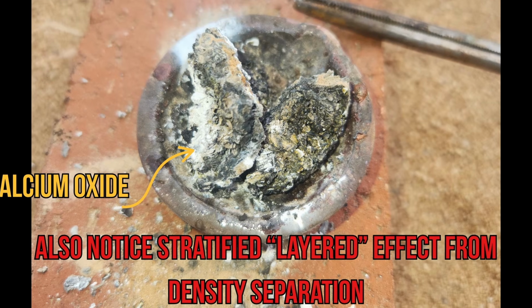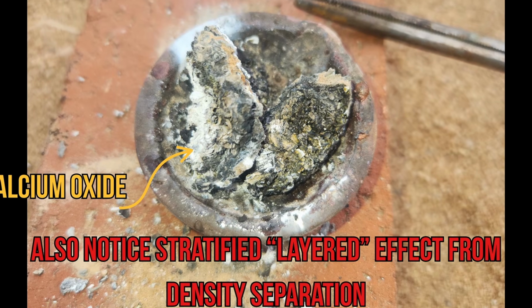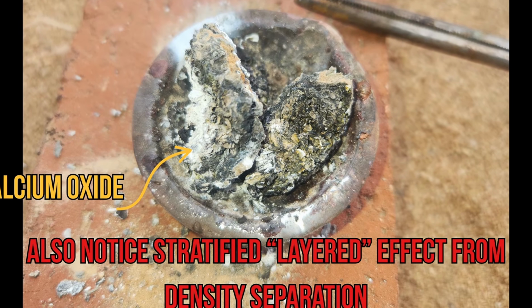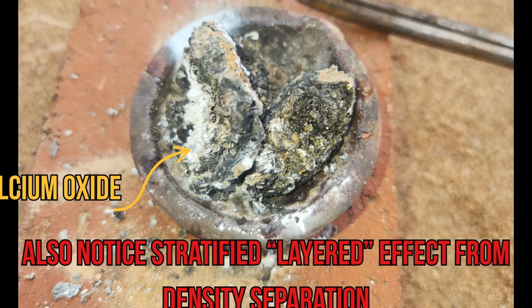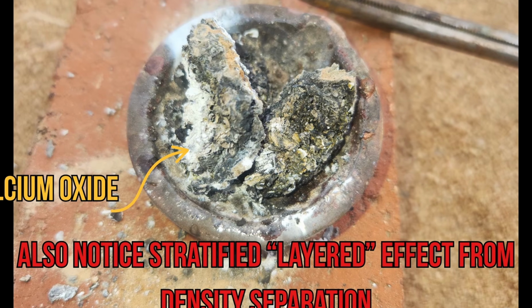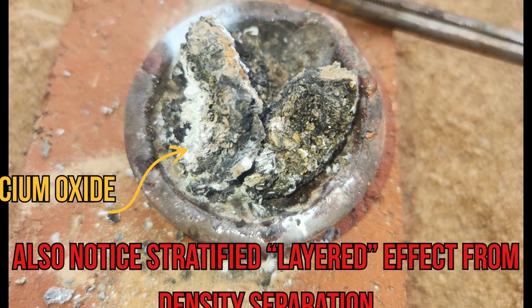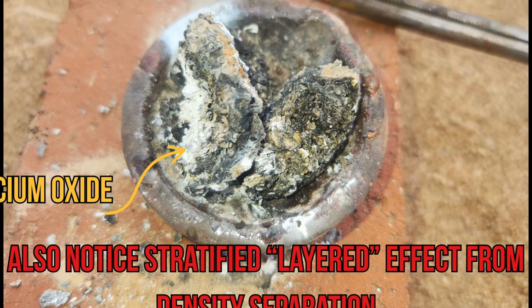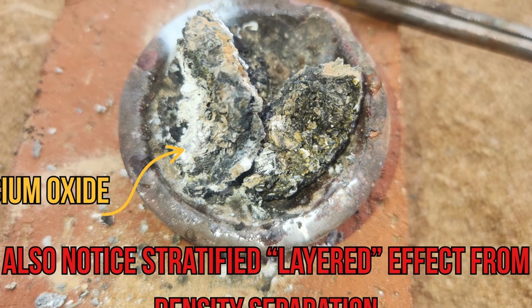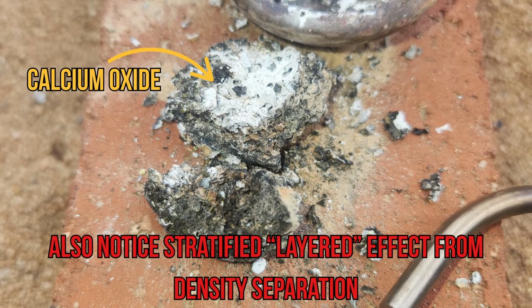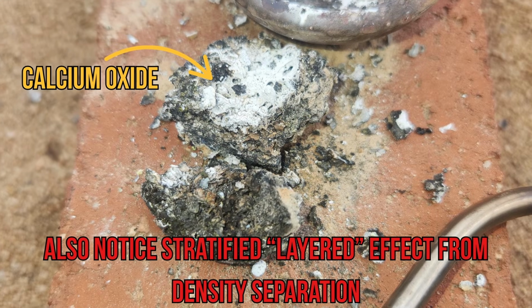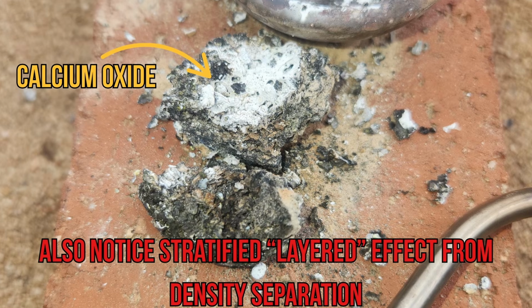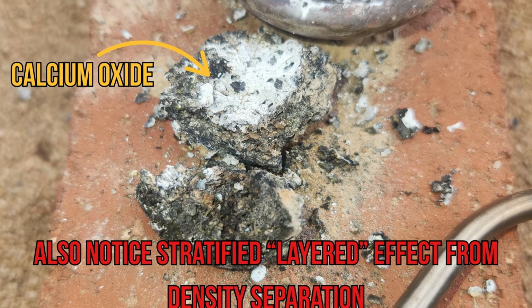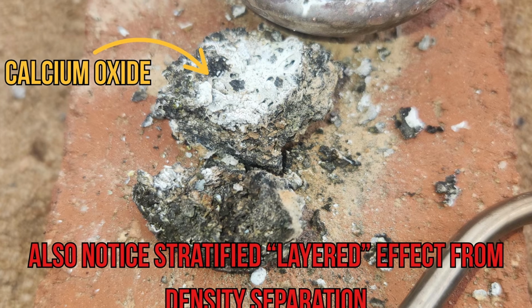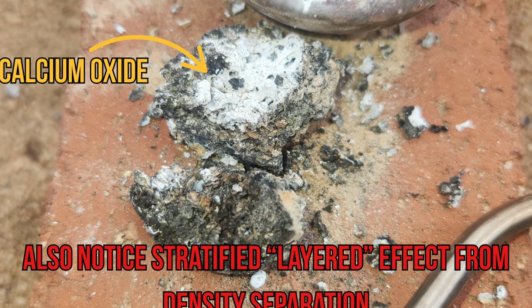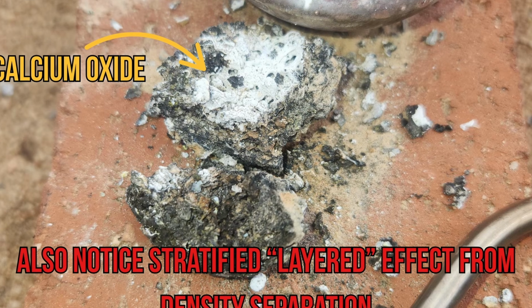But I think that was because of the oxygen in the atmosphere, since we didn't do this calciothermic reduction under vacuum. Yeah, there was more atmospheric oxygen for it to react with, so it created higher temperatures, which created some of the silica diffusion. But if done under vacuum, which is still theoretical because we haven't done it under vacuum, it's a thermite reaction basically. Theoretically, the calcium oxide should completely separate from the alloy cake. Oh, absolutely. And most of it did in our process. We just did find that there was some silica bound to the calcium oxide.